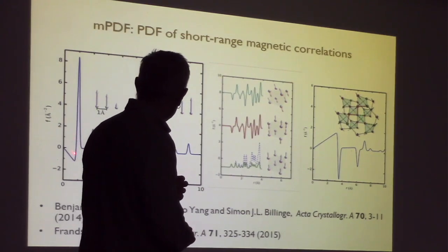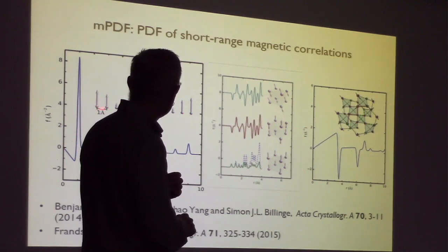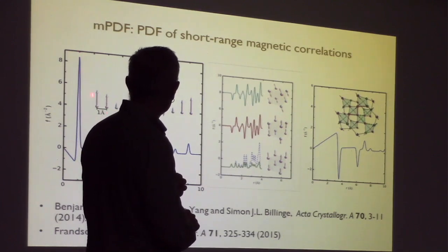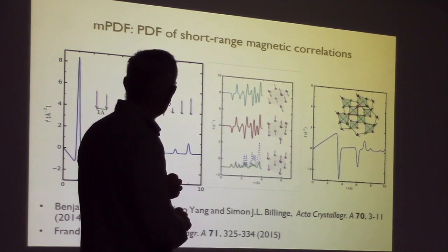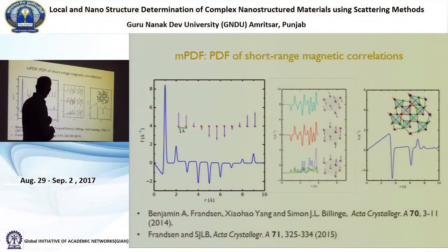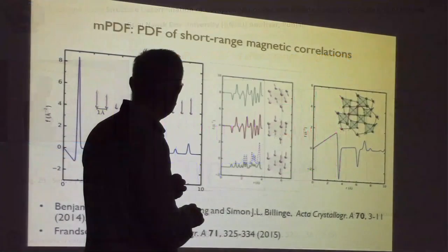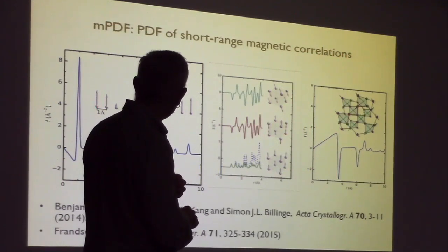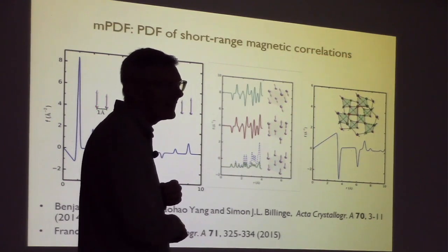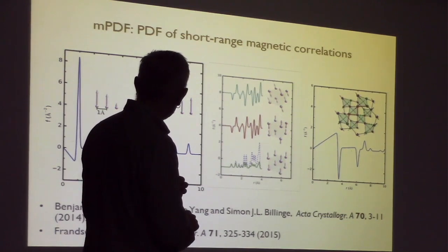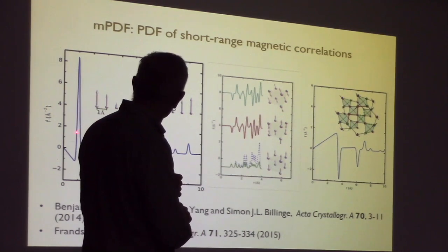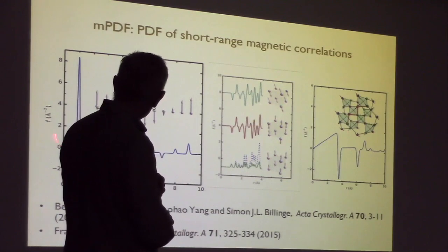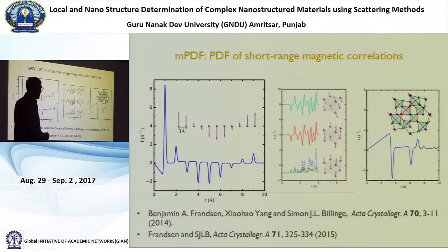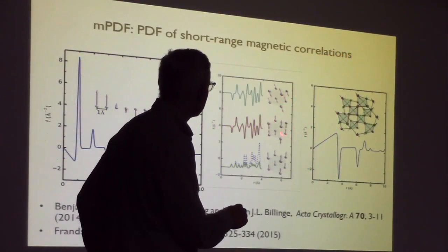And the way that the MPDF equations work is that when you have two spins separated by some distance, you get a very strong positive peak if it's a ferromagnetic correlation, and you get a negative peak if it's an antiferromagnetic correlation. So this guy, at one angstrom here, these guys are ferromagnetically correlated. These guys are ferromagnetically, these guys are ferromagnetically. But if you sit on this atom and look at that atom, this atom and that atom are anti-ferromagnetically correlated, right? And so this one is this guy here, let's say 4 or 5. So the MPDF gives you nearest neighbor ferromagnetism and then far neighbor anti-ferromagnetism. This funny baseline is actually real, and it's also useful, but it's coming from the MPDF equations. But you can straightforwardly compute the MPDF from different structures.